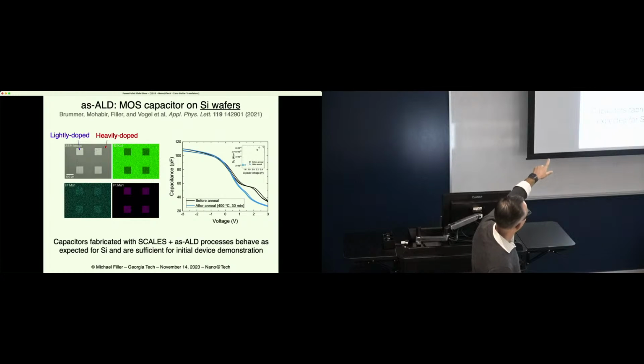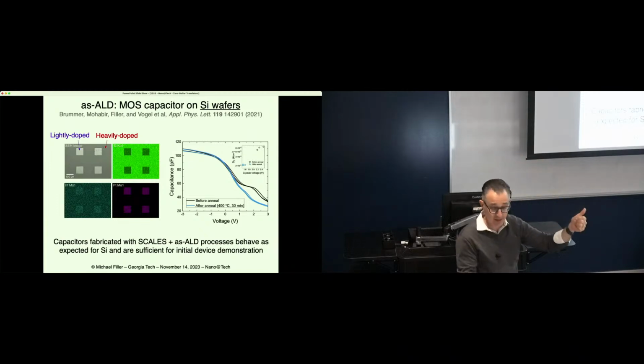So this is what those look like if you do EDS in the SEM. So we have these squares that are selectively deposited. And when we do capacitance measurements, we can characterize the capacitor and see, for example, that one, it behaves pretty decently. It behaves like a capacitor, so that's nice.